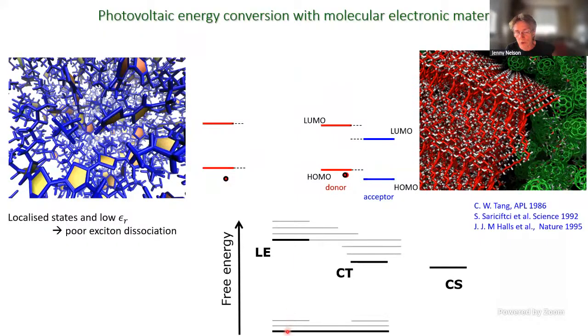So now we not only have a ground state and an excited state, but we also have configurations where we could have an electron on one side and the hole on the other side of this heterojunction. And we usually call that a charge transfer state. So it's a state that's stabilized at the interface. And then eventually, when the electron and hole escape from each other, we have what we call a charge-separated state. And that's actually what we want, because we want to be able to carry the electrons away so they can contribute to an external circuit.